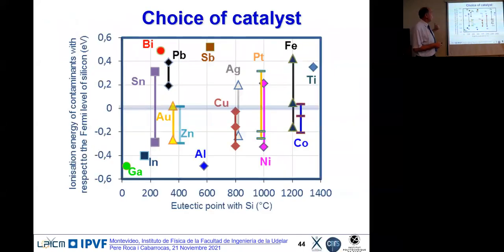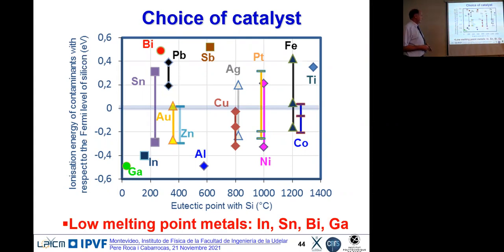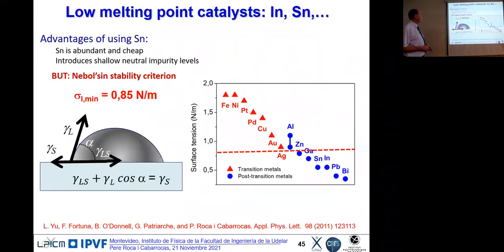But we wanted to be at low temperature. We started with tin, bismuth. So tin doesn't introduce defects. Bismuth is neutral. Gallium can introduce p-type doping in the nanowire. And so those are all low melting point metals.